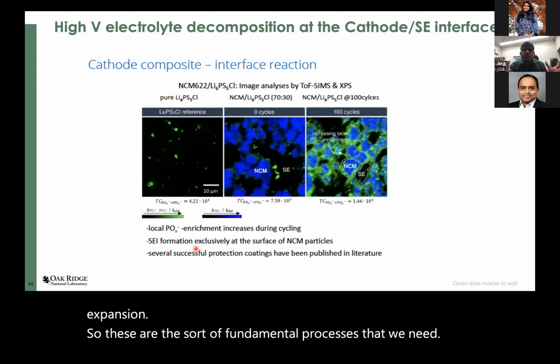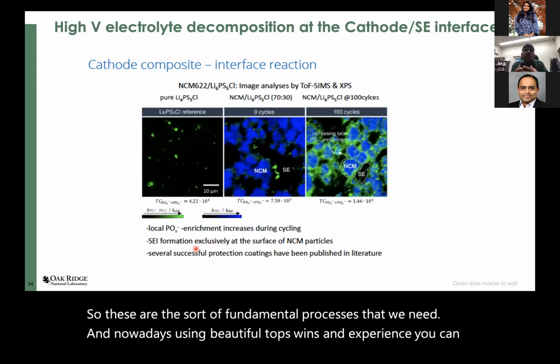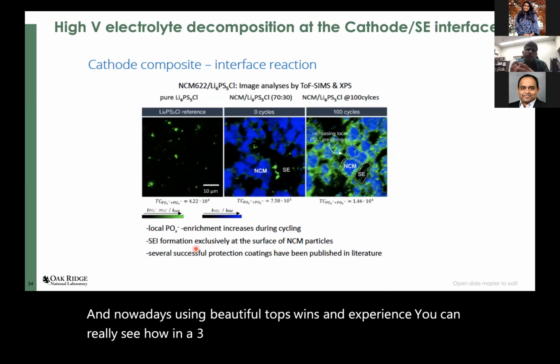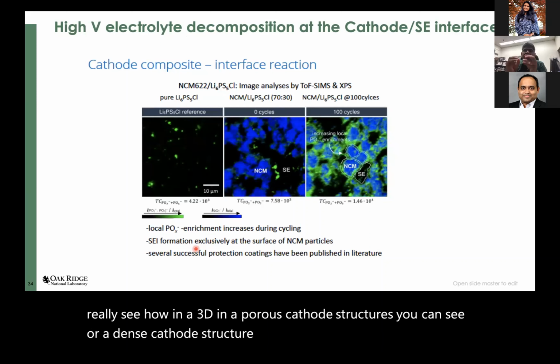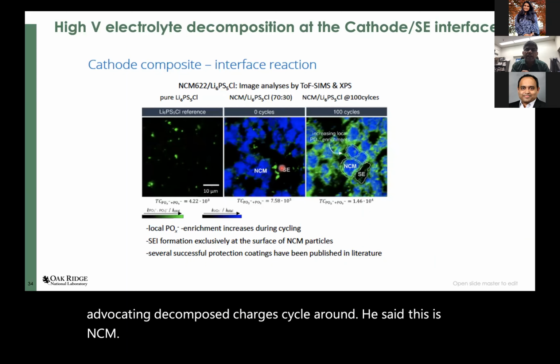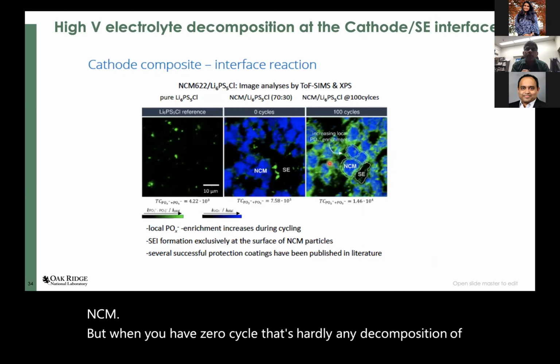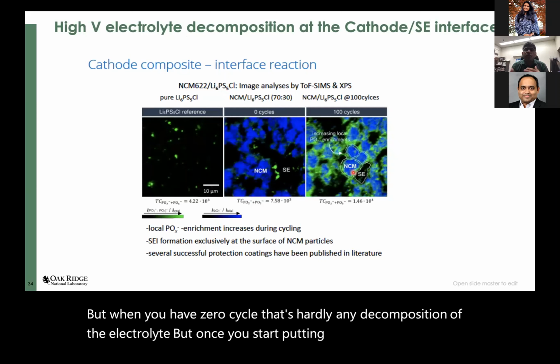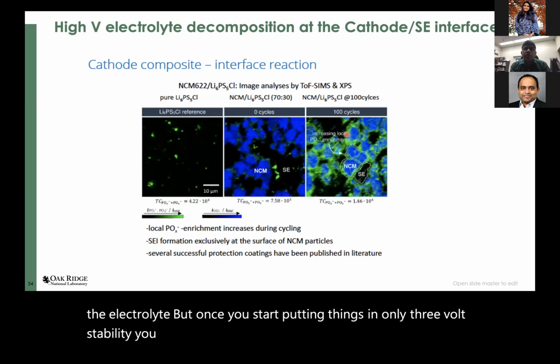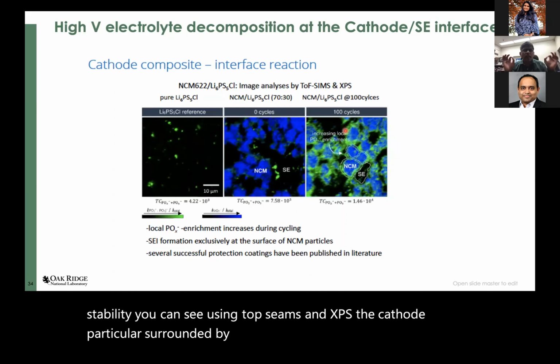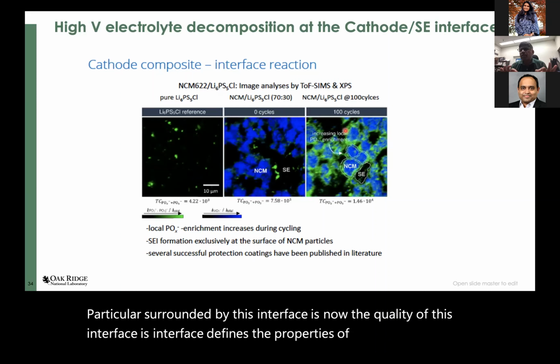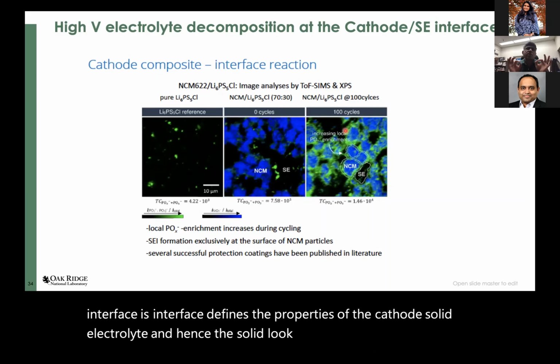And nowadays, using beautiful TOF-SIMS and XPS, you can really see, in 3D, in a porous cathode structure or a dense cathode structure, that the solid electrolyte is getting decomposed as you cycle. So this is NCM. When you have zero cycles, there's hardly any decomposition of the electrolyte. But once you start cycling, with only 3 volt stability, you can see using TOF-SIMS and XPS that the cathode particles are surrounded by these interfaces. Now, the quality of these interfaces defines the properties of the cathode solid electrolyte interface, and hence the solid-state cell performance.